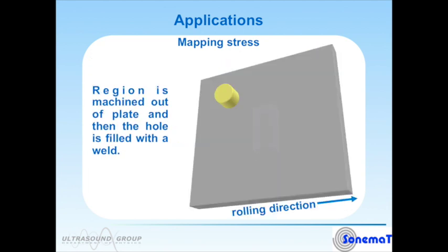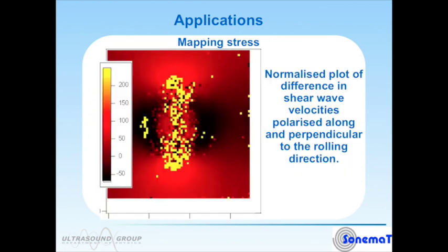As an example of mapping stress, we took a thick aluminium plate, machined out a region of the plate, and in doing so relieved some of the internal stress. This was then refilled with a new weld and then machined flat. So superficially, the plate looked like it had done so originally. This is a common approach for trying to generate stress fields in metal plates. If we scan the metal plate and look at the degree of shear wave velocity difference and plot it in this simplified relative map, we can see a distribution of stress that matches exactly with what one would expect from the theory. The middle region looks noisy. That's because the quality of the weld here was very poor, and as such there was lots of scattering within the weld region itself.